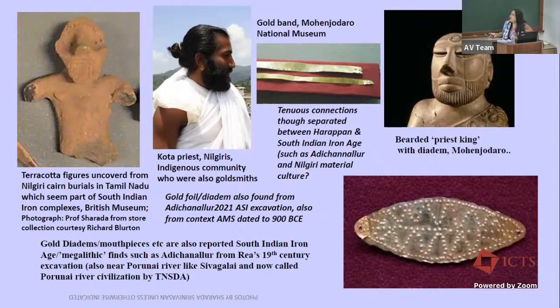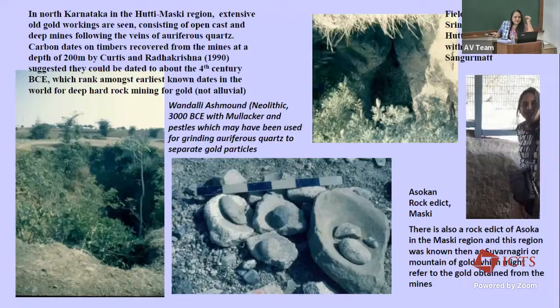Now, in Adichinalur also, there are a lot of finds of what we call mouthpieces or diadems, which were reported by Alexander Rea. And several of these are in the Government Museum at Chennai. And that's why what you're seeing with Adichinalur and Shivagalai is also some continuity in these finds of gold diadems. And at Adichinalur also, the gold finds were then AMS dated to about 900 BC.